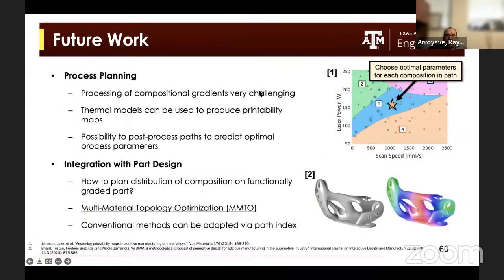So, future work in this context of functionally grading: we have done compositionally grading, but if we're trying to print this, we have to map the processing space in such a way that we minimize the formation of these microscopic defects. So the idea is to combine composition path planning with process path planning in such a way that we obtain not only optimal chemistries, but also optimal processing conditions at every material point, in such a way that we optimize a particular property while avoiding these undesirable obstacles, while at the same time ensuring that the composition path is printable.